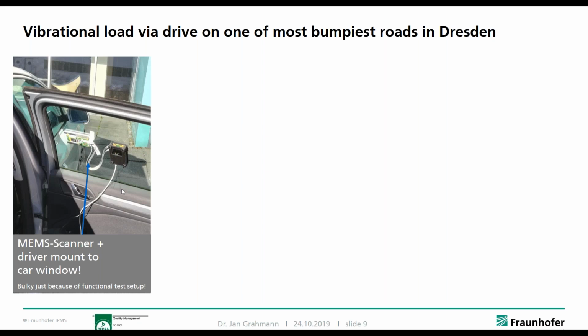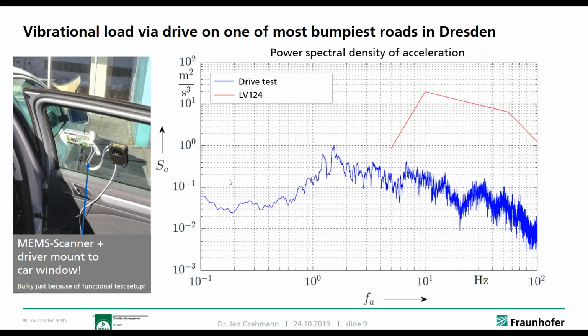So we used our integrated position sensors and accelerometers, again, to see how the scanner really moves and in what directions. And secondly, what is the actual load driving down a very bumpy road in Dresden. And here you've got the power spectral density. Here you've got in red the standard again as reference, which is used for the destructive testing. And the blue line is the power spectral density we measured driving down a very bumpy road, showing that there are 2 orders of magnitude between the actual test requirements and where we are in the range really using a car, having it mounted to basically the window here, the car casing.